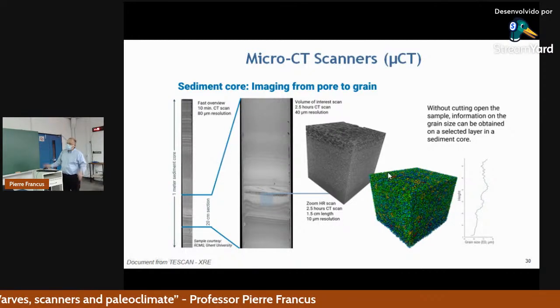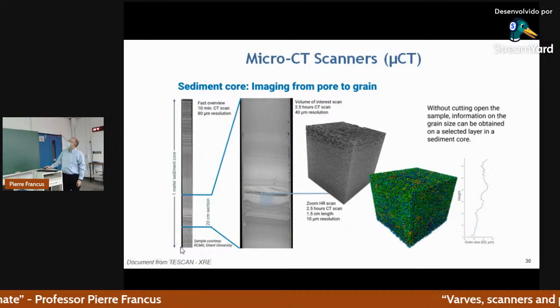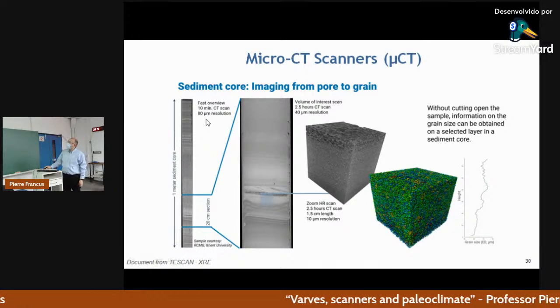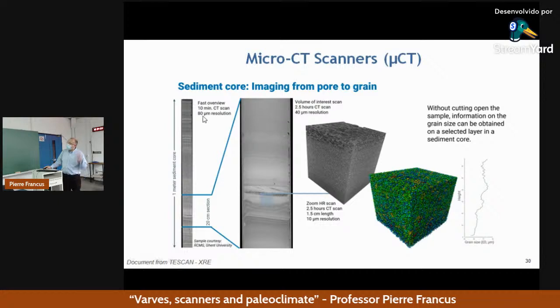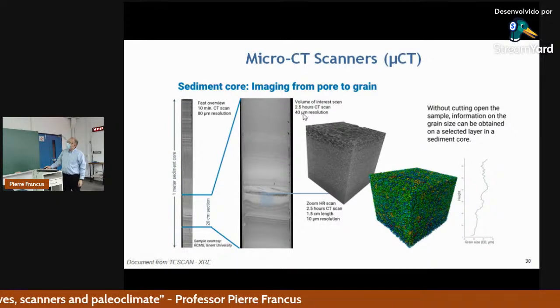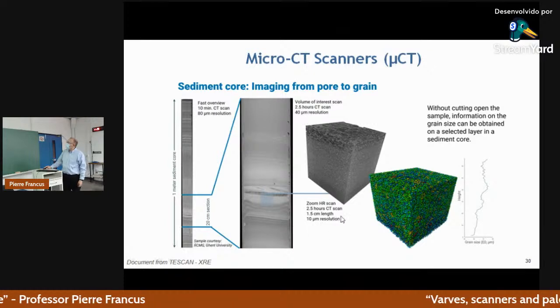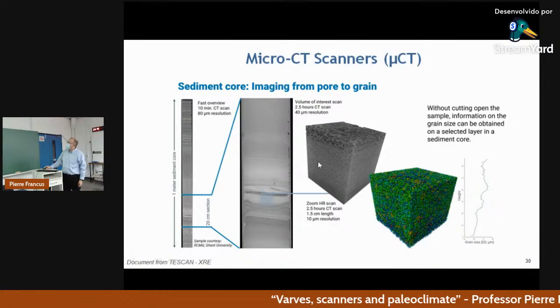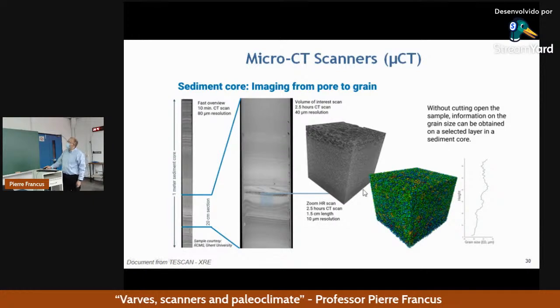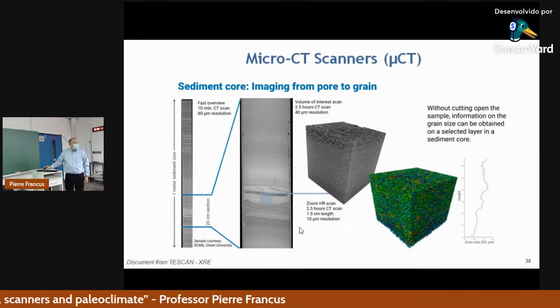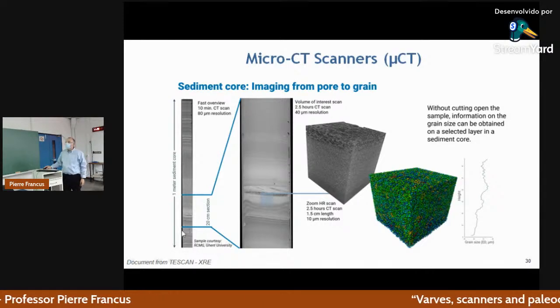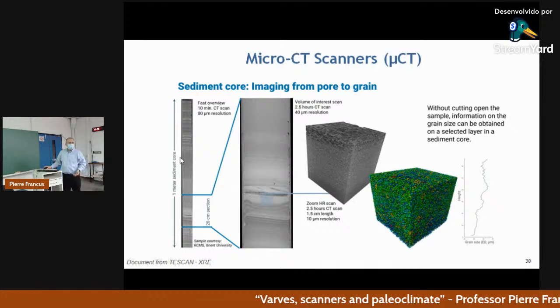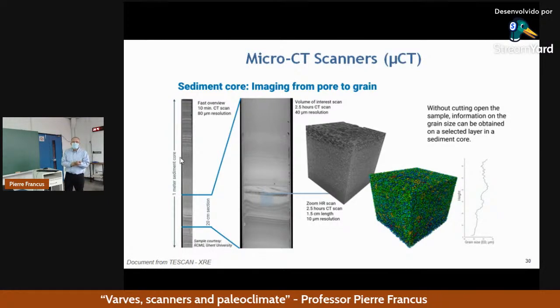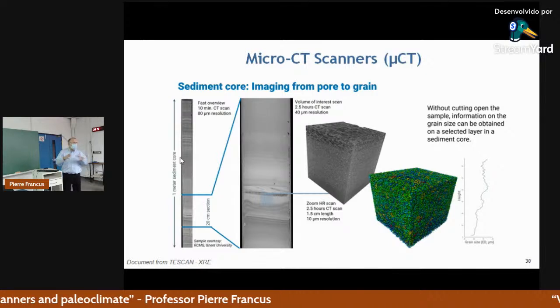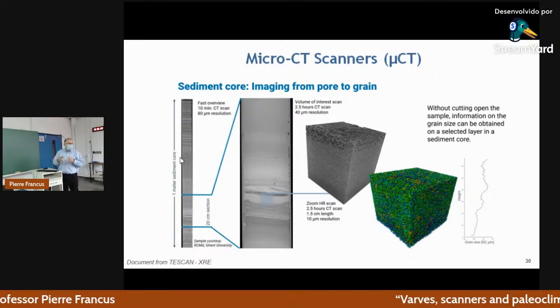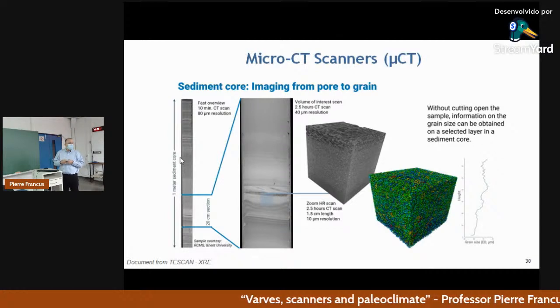Why do we do this kind of zoom in? Because it takes 10 minutes to scan the core with a voxel size that is 80 microns on a side. It takes 2 hours and a half if you go down to 40 microns, and it takes 2 hours and a half for a very, very small region of interest if you want to go down to 10 micron resolution. So it's impossible to scan the whole core at the maximum resolution. That's the take-home message. You will also get files that are way too big to be handled, even with very powerful computers.